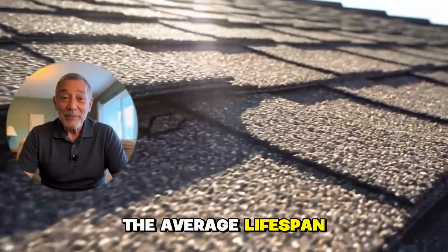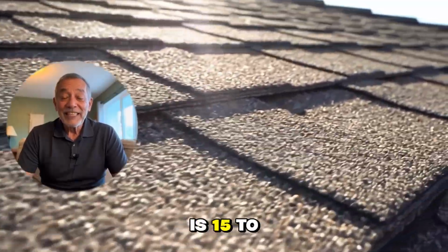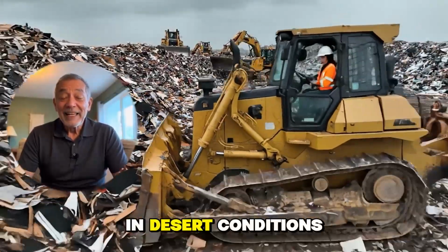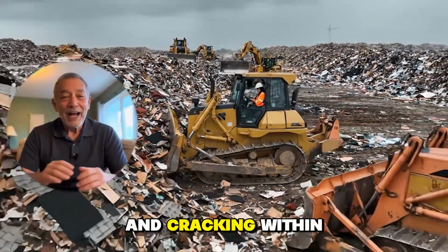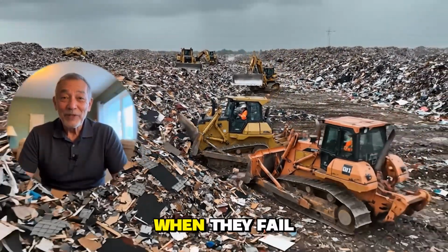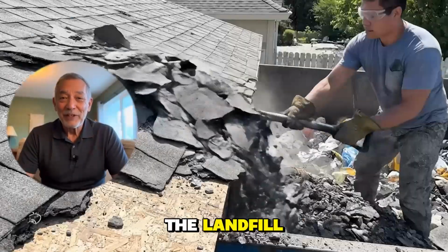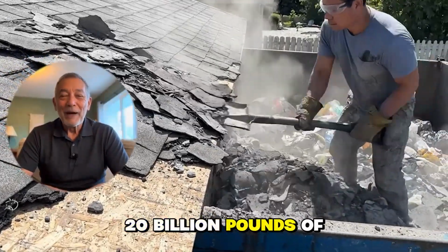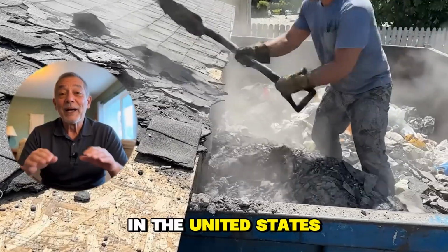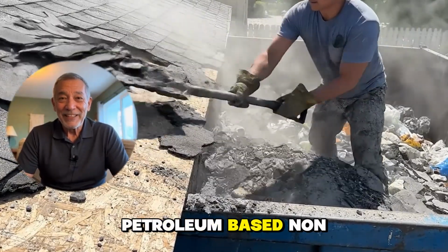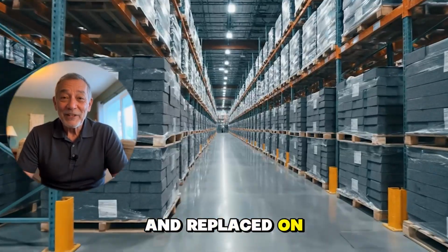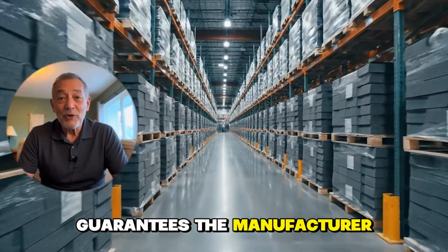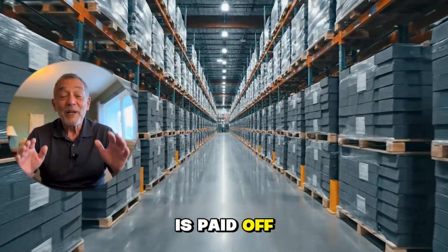The average lifespan of asphalt shingles is 15 to 20 years. In desert conditions, they start curling and cracking within 3 to 5 years. When they fail, they go to the landfill. 20 billion pounds of roofing waste annually in the United States, petroleum-based, non-recyclable, and replaced on a cycle that guarantees the manufacturer another sale before the mortgage is paid off.